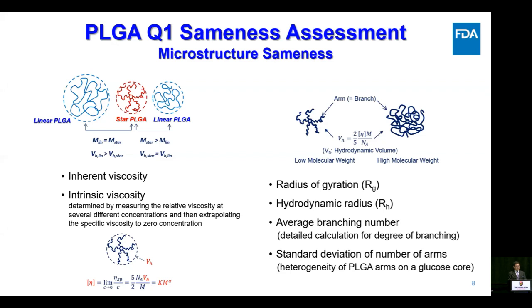The big difference is that star PLGA has multiple linear PLGA chains anchored to the core. So due to this feature, and also the steric hindrance on the movement of the linear chains, there is something different. One is that compared the first and second, which have a similar molecular weight, the hydrodynamic volume of the linear PLGA is much larger. And oppositely, you can see in the middle one and right one, the hydrodynamic volume looks pretty similar, but the molecular weight of the star PLGA is much larger than the linear PLGA. And so a conventional size exclusion chromatograph alone cannot characterize the PLGA.